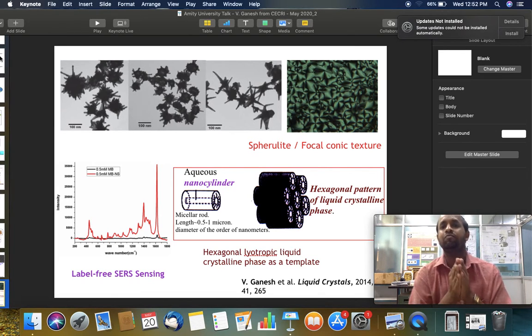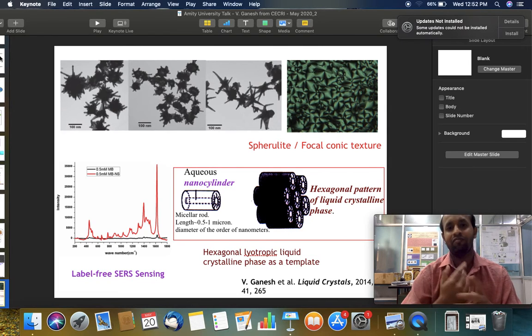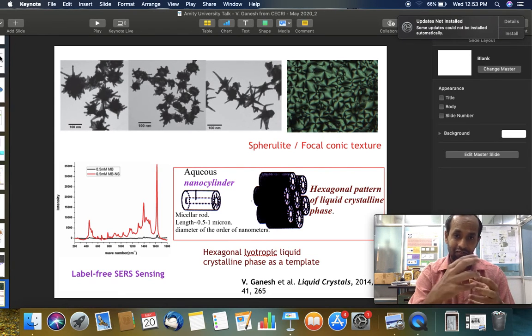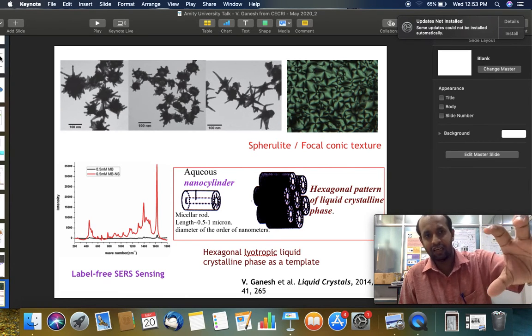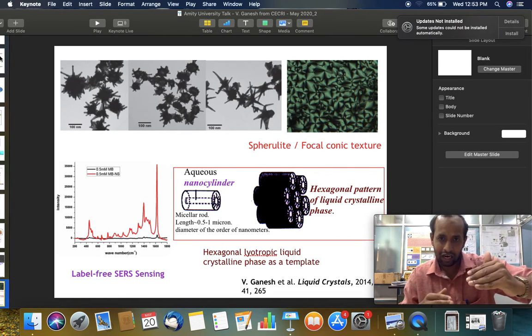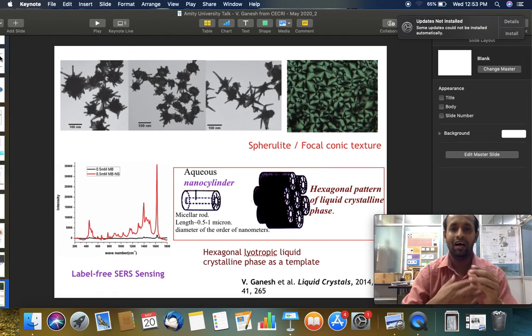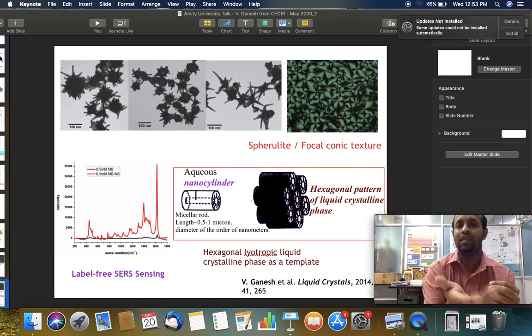Okay, so among many different nanomaterials, the gold nanostars attract the attention of researchers nowadays. It is very simple to prepare. In fact, we came up with a simple strategy using a template, using a hexagonal lyotropic liquid crystalline phase as a template, which is nothing but a mixture of water and a surfactant mixture. By varying the concentration of this mixture, by adding a different concentration of the salt, and allowing different time durations for the reduction reaction, one is able to tune the formation of nanostars. You can see a bulky core and a smaller arm, on the other hand a smaller core and a bulky arm. By tuning such kind of shapes, you are able to modulate the electron transfer reaction.